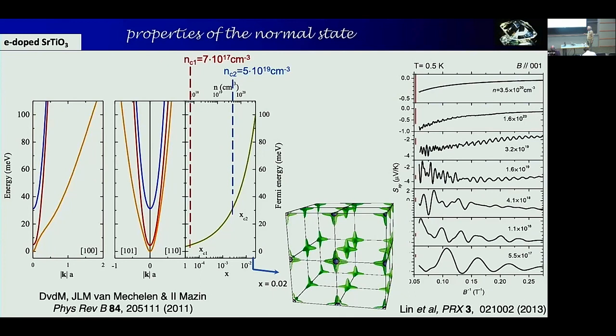And so this is on a very expanded scale along different directions, these 2 panels. The splittings that you see here, the big one is caused by spin-orbit splitting on the titanium 3D shell. And the small splitting has to do with a small distortion in the material. If you go below 100 Kelvin, it's no longer cubic, it becomes slightly tetragonal, and that causes the splitting over here. So if you now dope electrons in there, you can calculate from this band structure what happens.